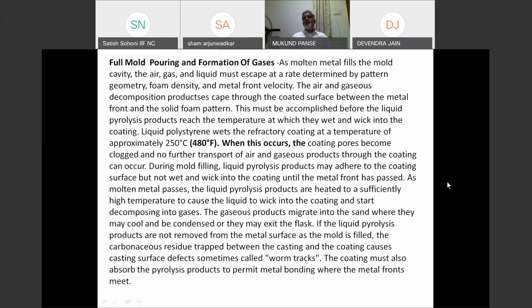The gas formed by the foam should pass through this coat. There is no other way for the gas to go. When the gas forms at the lower temperature through the coating, lustrous carbon is not formed. Liquid film is not formed, and you don't get lustrous carbon on the casting surface, which gives a bad surface in full mold casting. These specialized coatings are developed by various people, mainly Foseco and others.